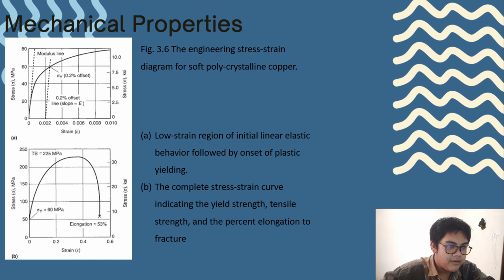Now we got to mechanical properties on figure 3.6. The engineering stress strain diagram for soft polycrystalline copper. The low strain region is the A figure. Low strain region of initial linear elastic behavior followed by onset of plastic yielding, and the point B on figure B, the complete stress strain curve indicating the yield strength, tensile strength, and the percent elongation to fracture.